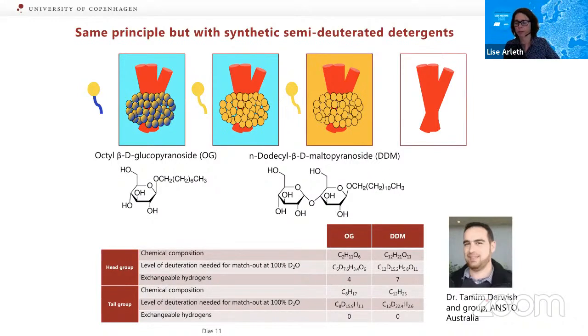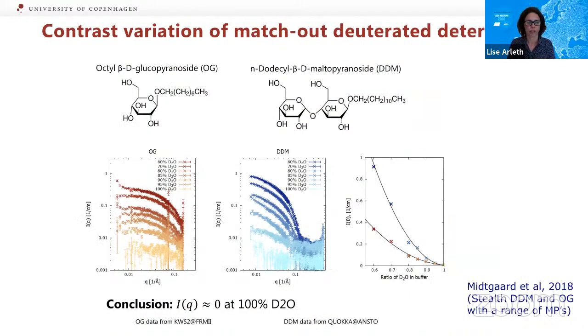So we teamed up with Tamim Darwish and his group from ANSTO, and then we prepared octyl glucoside in an deuterated form and DDM in an deuterated form. And again, we had to measure and calculate how we could separately match out deuterated head groups and tails. But this was indeed possible to do, as is demonstrated on these contrast variation SANS data here, where we can show that both for the OG detergent and for the DDM detergent, as we go towards 100% D2O, they both become invisible, and the scattering from them is not stronger than from the background.